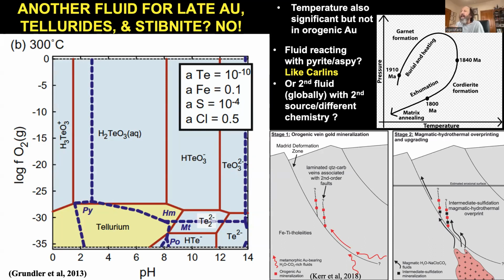What happens is you may deposit silica, you may deposit gold, you may deposit lots of pyrite and arsenopyrite. Then the next pulse of fluid comes into a vein and reacts with the earlier pyrite and arsenopyrite. To get tellurium out of solution, to get antimony out of solution, you need to drop temperature, which we said does not happen for tens of millions of years during uplift, or reduce the fluid. So if the next pulse of fluid getting into the quartz reacts with the early pyrite and arsenopyrite, it'll help get the tellurium and antimony out that didn't come out earlier. That's why it always looks later than the pyrite and arsenopyrite and much of the gold. But it's not a different fluid. It's the same fluid. It's just reacting with the earlier minerals.